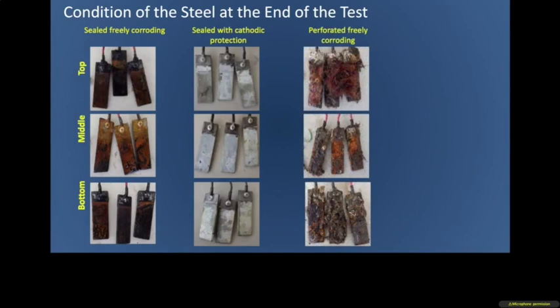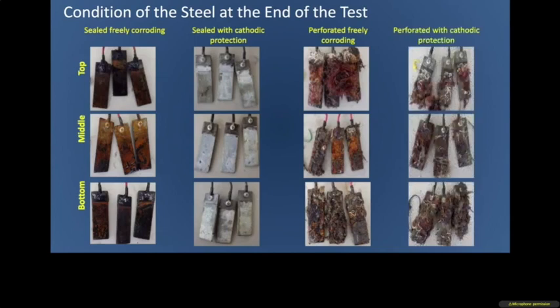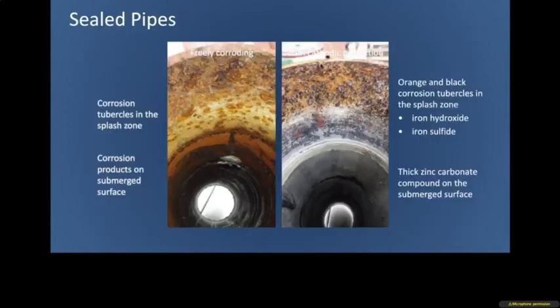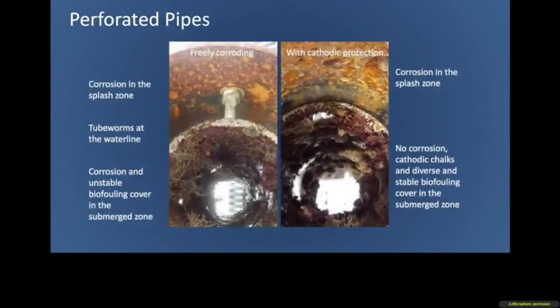Within the perforated freely corroding samples, we got marine growth, but the marine growth typically was shed as the steel corroded and it exfoliated all the organisms. And the perforated with cathodic protection, which again is our concept, we got pretty well zero corrosion and a very healthy assemblage of marine organisms. If you look inside the steel pipes, these are the sealed pipes. If you look inside the perforated pipes, you can see the contribution of marine growth. And the one on the right with cathodic protection had no corrosion, it had cathodic chalks, and it created a very diverse and stable biofouling coverage in the submerged zone.